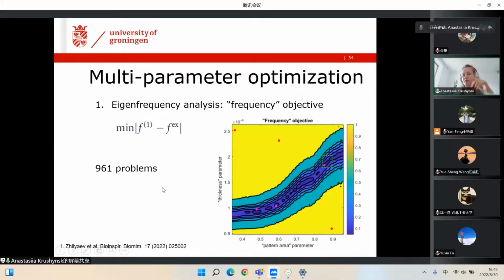So for that, we solved about 1,000 problems and constructed the frequency objective map, which shows us that in the yellow region, we are at least 1 Hertz away from the excitation frequency. While in the dark blue region, we are very close, so smaller than 0.1 Hertz difference to the excitation frequency, so really resonance type conditions. And for these conditions, let's have a look how closeness or staying away from the resonance influence the flight dynamics.